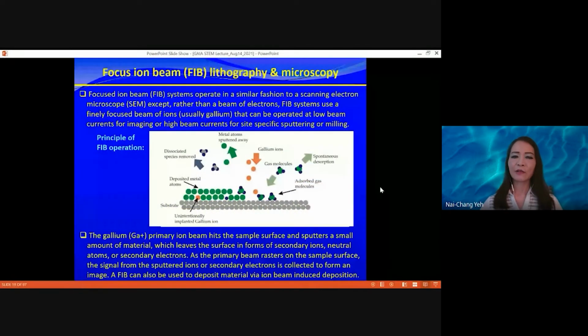Okay, now there's also focus ion beam lithography. With focus ion beam, if you use gallium ions, it's much heavier than electrons, and so you can have much shorter de Broglie wavelengths. However, because it's much heavier, if you have comparable energy as the electron energy, then you can cause a lot of damage to the surface. Sometimes you can take advantage of the damage if you really want to remove a lot of material. So you have the material and then you have the gallium beam coming in, and then you can sputter the atoms away as well as some secondary electrons.